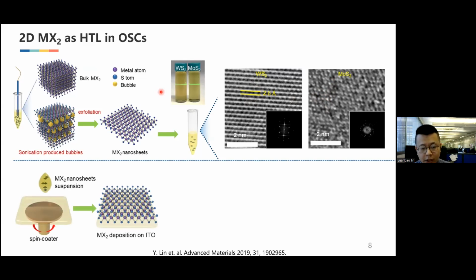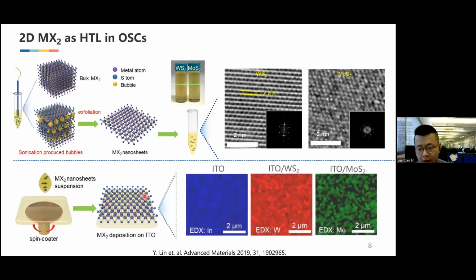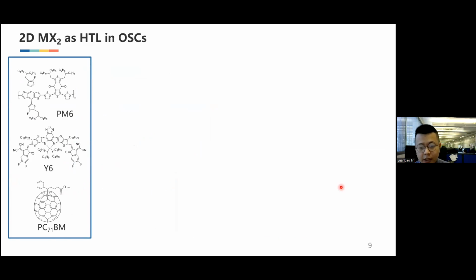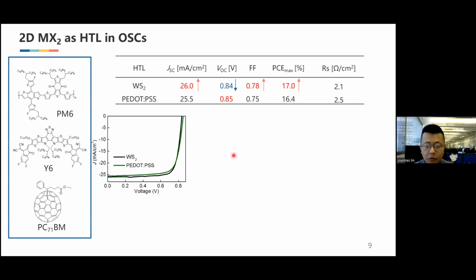And then we tried to spin coat this 2D material suspension on the ITO. From the EDS mapping, the coverage of the tungsten disulfide is comparable to the ITO, but for MoS2, we can see some dark area. It means poor coverage on the ITO. We tested it with one of the highest performance systems in 2019, PM6:Y6, and PC71BM. And we get higher performance as compared to PEDOT:PSS because of the increase of the photocurrent, and also better fill factor, but slightly reduced VOC.